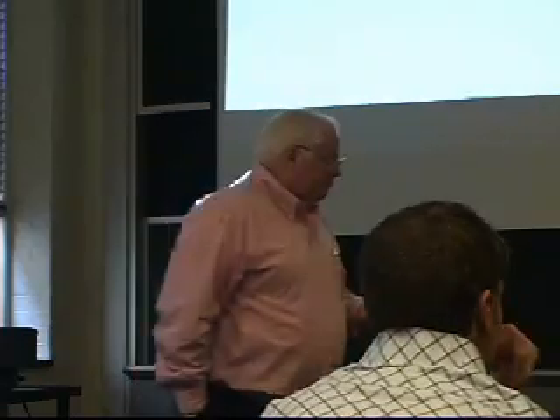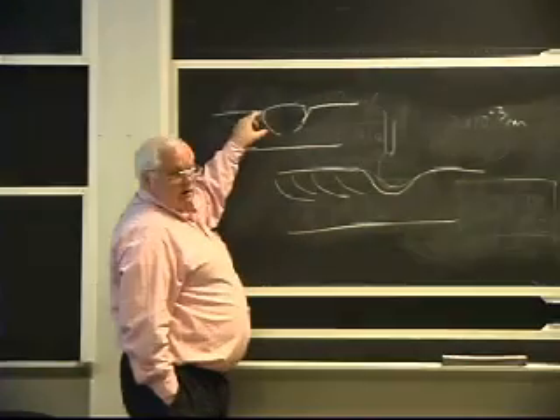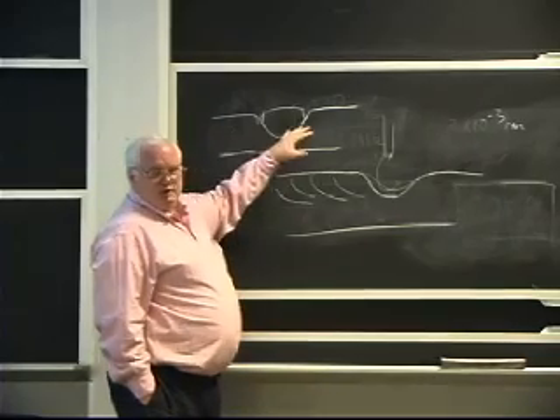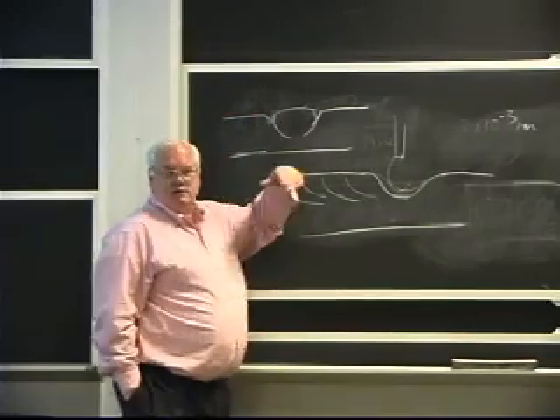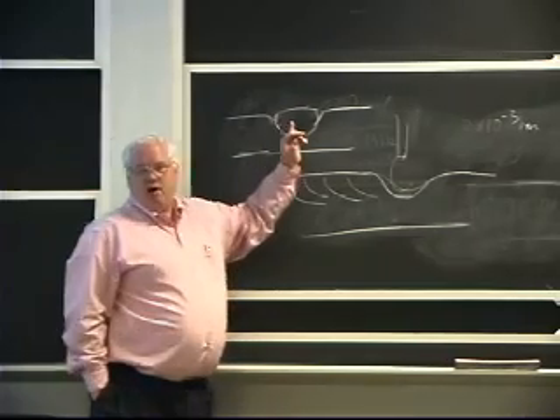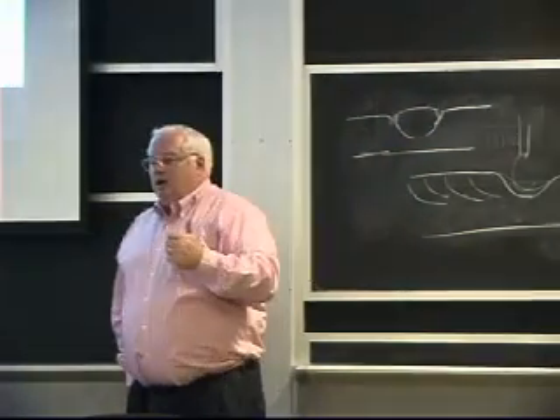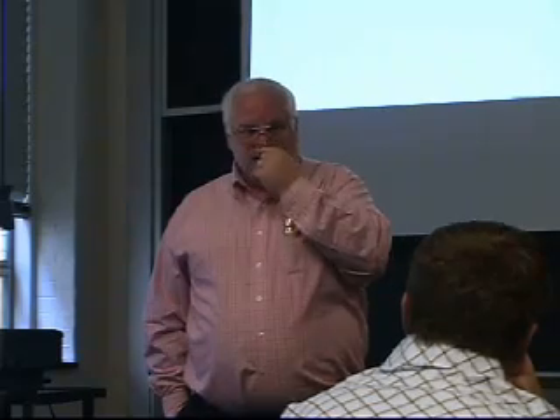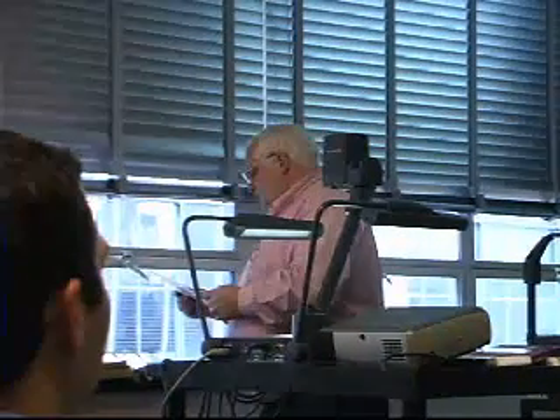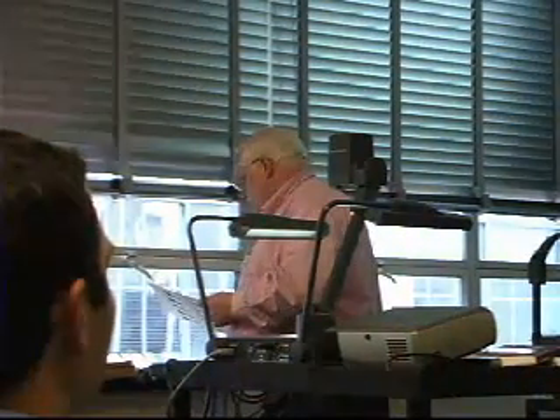Anyway, this thing had an undercut, and then they coat the whole thing, in the old days used to be coal tar, but they put a corrosive protection coating on these things. And over time, the coating may come off, and in fact, it did come off, and there was corrosion here. So then the question became, was there undercut from the original manufacturer of the steel in the steel mill 27 years before? Or did this thing fail because it had a corrosion at the toe of the weld, which led to a fatigue crack? Everyone agreed it was a fatigue crack that caused it to grow, but then it was chicken or egg. Was it corrosion or was it undercut that got the crack started? And it turns out I was able to prove it was undercut by looking at other parts of the pipe and also by fracture mechanics, so far as that goes.